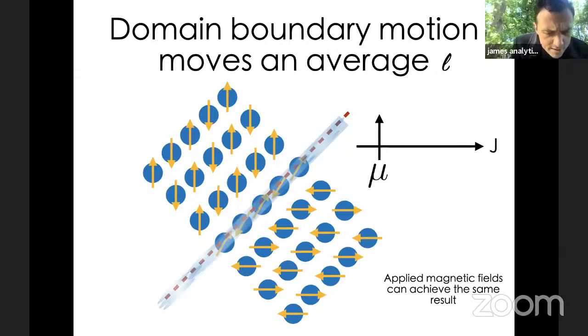So I think at this stage, it's probably good to just introduce one other parameter, which is how the system responds to an applied magnetic field. So remember, I showed you when we were looking at the Landau-Lifshitz-Gilbert terms, one of the terms was like a field-like term. So you actually do expect that maybe by the application of a magnetic field, you can also orient the Néel vector in the same way, just by coupling to the anisotropic susceptibility of the antiferromagnetic system.